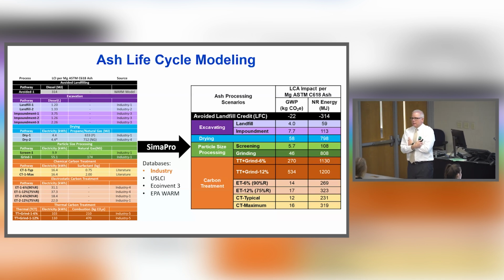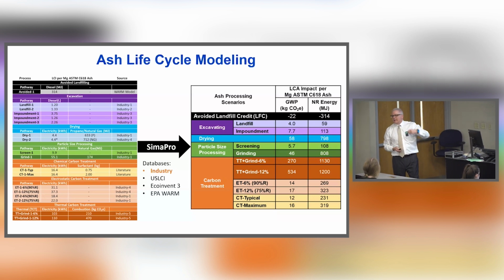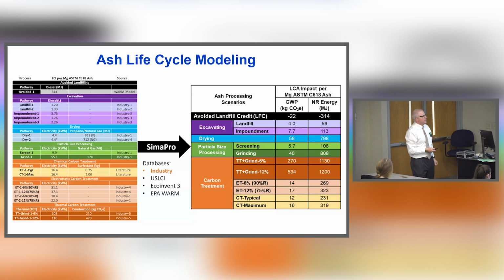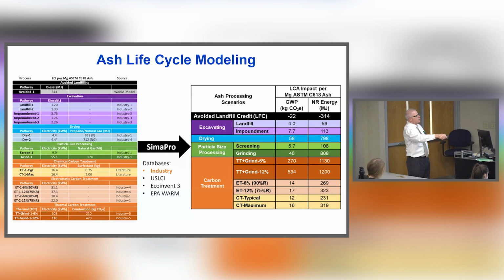Does anybody know what thermal treatment is? That's a very elegant word for saying I'm going to burn it, right? I got carbon in there. I already burned carbon at my power plant. All right, I'll just burn a little bit more, right? I'm going to burn off the residual carbon in the coal, and you can pull some of that heat back, which is good. We can use some of that in the drying. And we did that for low carbon, 6%, 12% carbon ashes.